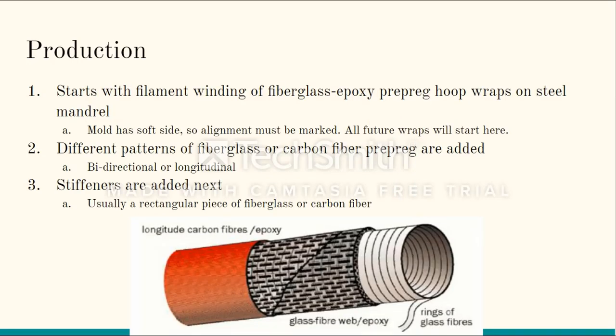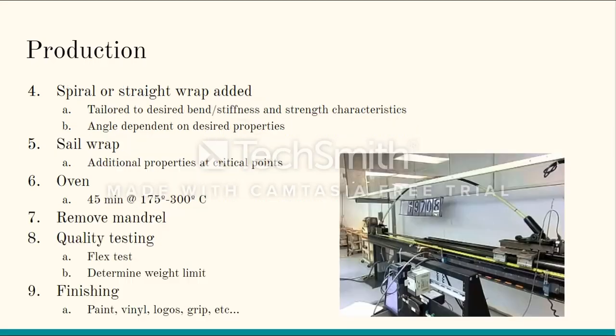Production of a pole starts with filament winding of a fiberglass epoxy pre-preg in the hoop direction on a steel mandrel. The mandrel has a soft side where the steel bends under its own weight, so the alignment must be marked. All future wraps will start here. Different patterns of fiberglass or carbon fiber pre-preg are added in, either with a bidirectional weave or a longitudinal weave. Stiffeners are added next, and this is usually a rectangular piece of fiberglass or carbon fiber to add extra stiffness.